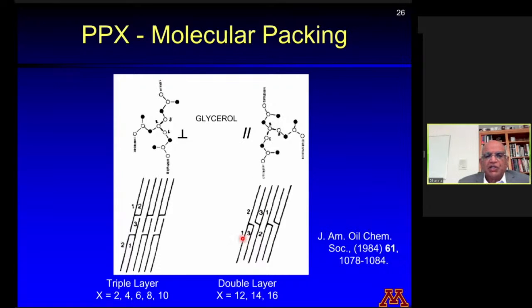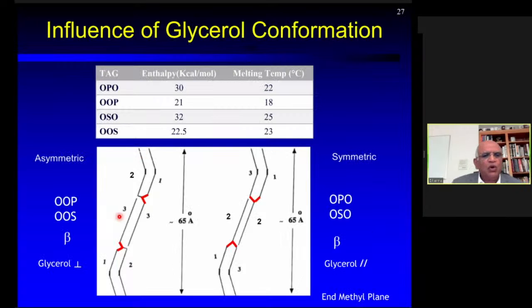As we have seen in the single crystal structure, when 1 and 3 chains are together, the glycerol carbons pack in a parallel orientation with respect to the methyl plane. However, when it is a 3-layer structure with the 3rd acyl chain segregated and 1 and 2 chains packed together, this forces the glycerol conformation to take a perpendicular orientation to the methyl plane, as is shown here. So what is the implication of the glycerol packing parallel to the methyl plane or perpendicular? What difference it makes is shown in this slide here. We took 2 pairs of triacylglycerols, this pair is asymmetric, this pair is symmetric.